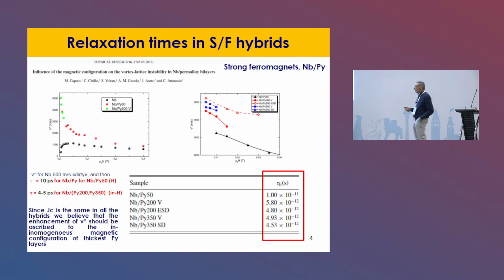I should also say that in this case, niobium was deliberately fabricated as dirty. This niobium was dirtier than the previous one, so maybe this plays a role, not maybe, this for sure plays a role in increasing the critical velocity. But as I said, the most important thing is this result. These 2 curves, the red ones, are measured on the same niobium permalloy bilayers. This is 200 nanometers thick.